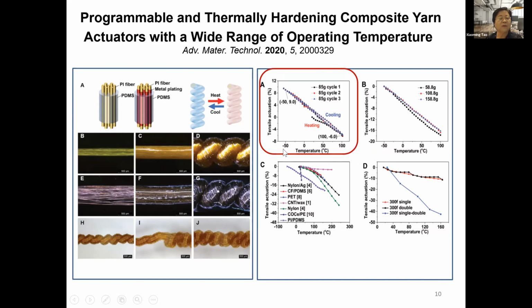Okay. And here, this diagram shows the response with the temperature. The actuator actually worked from -50 to 100 degrees. That is much wider than the previous actuator. And you can see the change in the length, we call it tensile actuation, is linear with the temperature over many cycles. Okay. This is nice, it can work at a lower temperature and also quite high temperature. Compared with the previous work, this diagram shows that comparison. The purple one is ours, because that's the only one that can work at a low temperature, -50 degrees C, and up to 100 degrees. And it has reasonable actuation and is also almost linear. This actuation curve is almost linear, so you can control it better.